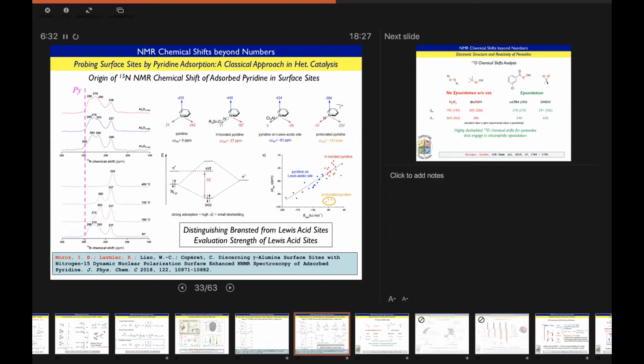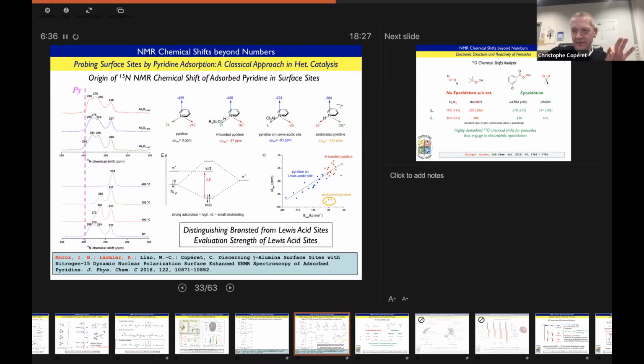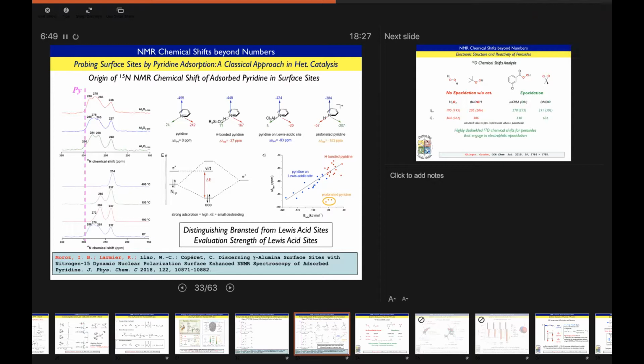So, yes, to answer your question, we definitely need DNP for a lot of these measurements, because we can extract the CSA by 2D NMR. And this is actually also with labels. So it's labeled pyridine on the surface with DNP.